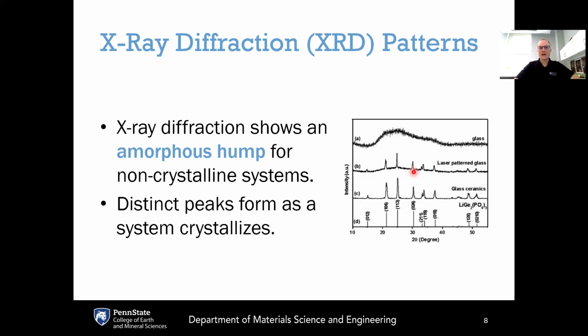What this means is that X-ray diffraction is actually a great tool to determine the crystallinity or lack of crystallinity of a sample. So if you are trying to make a glass, one of the first experiments that you should do on your sample is an X-ray diffraction experiment, because that will tell you, did you in fact make a glass, or did you make a crystal, or did you get something in between? So X-ray diffraction is one of the key tools, because it can very quickly and easily tell us if the sample we're making is a non-crystalline material or a crystalline material. And if it is a crystal, what are the types of crystals that are observed?